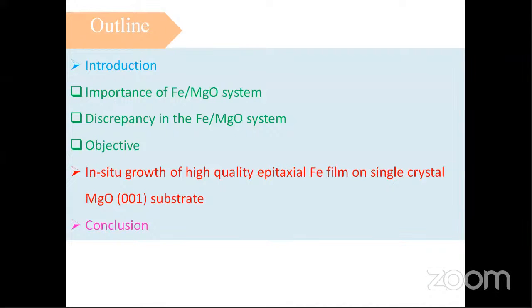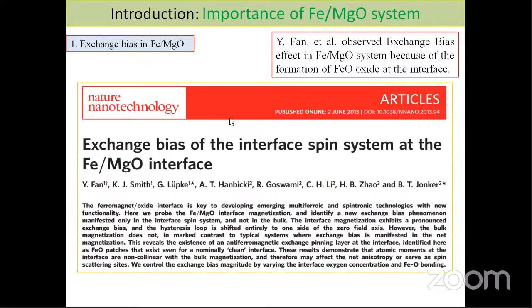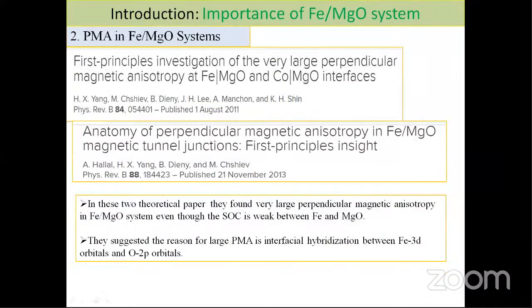The Fe/MgO system is very important because of the various properties observed in this system. For example, Y. Fan et al. observed exchange bias effect in the Fe/MgO system because of the formation of iron oxide at the interface. And other interesting properties have been observed, for example, perpendicular magnetic anisotropy in the Fe/MgO system. These two theoretical reports predicted a very large perpendicular magnetic anisotropy in the Fe/MgO system for a very thin film of iron, even though the spin orbit coupling in the Fe/MgO system is very weak.